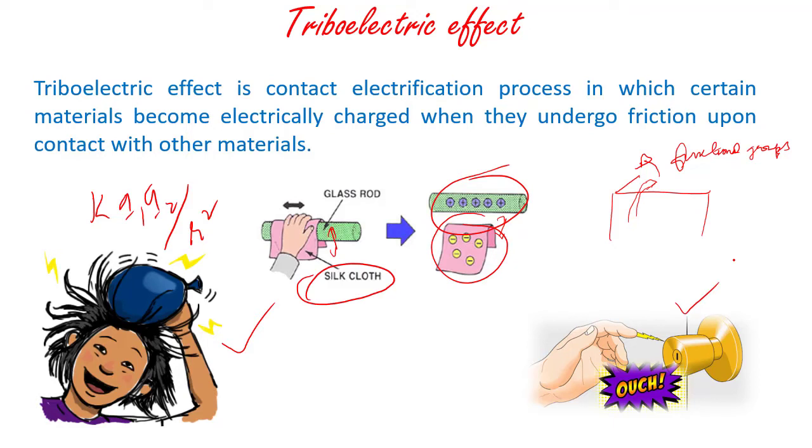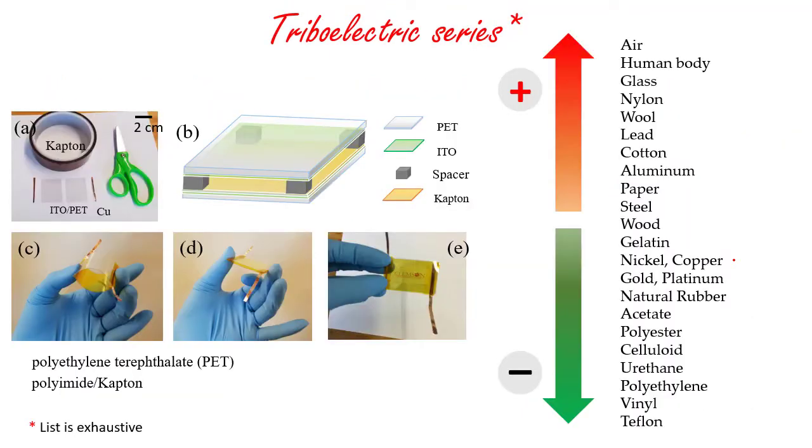But here what I want to show you is how we can take this triboelectric effect and convert that into devices. So one of the things that we did in our lab to take advantage of this is we coated just normal plastic that's there in water bottles. So this PET is there in water bottles. So we take PET from water bottles and then coat it with a nanometer thick layer of indium tin oxide. So ITO means indium tin oxide, and that's a conductive coating, and it keeps things transparent. So it's used in these transparent touch screens a lot.